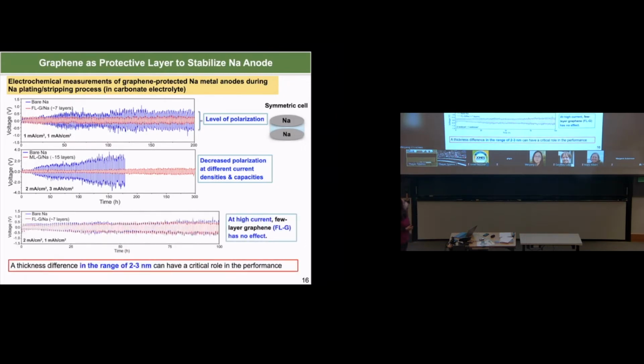But we do find, as I mentioned, that a thickness difference in only a range of 2 to 3 nanometer can have a critical role in the performance. You can see that when we try to cycle the battery at a high current, if we only use a few layer graphene that we prepared, it doesn't show much difference here. So in order to make the battery work, for example, in a high current or high capacity system, we really need to increase the thickness of the graphene film by around 2 to 3 nanometer. So the conclusion for this work is that in order to make the sodium metal system work, we need a more meticulous material design and to control the material property at a more meticulous level so that we can achieve a desirable performance.